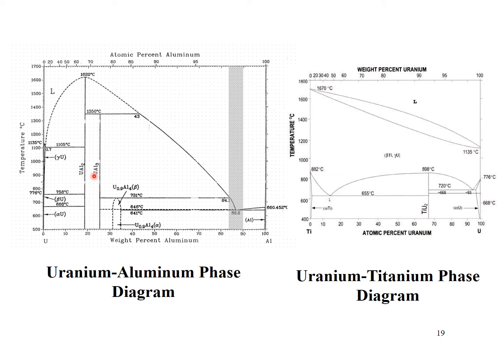If we mixed uranium with 25% aluminum by weight, it would fall right about here, and we would have a mixture of compounds based upon where it falls on this phase diagram. Over here, the 25 would be primarily the UAl3 with a little bit of the UAl2. And with titanium, we can form some of the alloyed species along with some intermetallic species. So again, depending upon the exact amount of material, generally alloys are better if you have a relatively low amount of material in the uranium metal. Even titanium, we said that it alloys, but at a high enough concentration, we start to form these intermetallic species.